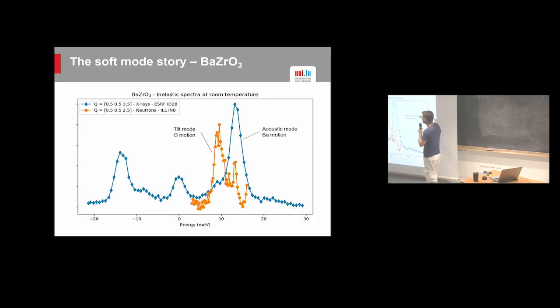Other comments, look at the resolution here. The blue curve is the X-ray again. Experimental resolution, 3 meV. That's not great because, essentially, the width here is really only instrumental. So you really cannot say much about the width of your phonon at all, but you do see that the peak in neutron, even if it's not the best, is really much sharper. So if you want energy resolution, you have to go for neutrons. There's no way around it.